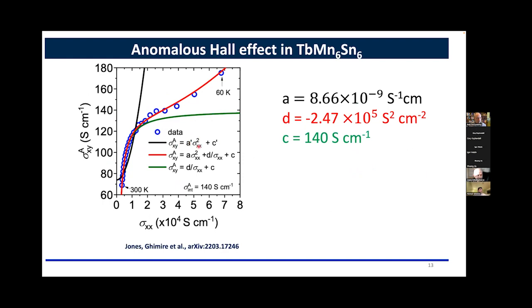So in the literature, we have seen this contribution a lot of the time, and in it we have the C part, which is the intercept, and the intercept gives the intrinsic contribution. Whereas the A term, which comes with the sigma xx squared terms, is believed to come from some sort of impurity scattering, skew scattering, side jump, and so on. But when we try to fit our data, this line doesn't fit well, as you can see here.